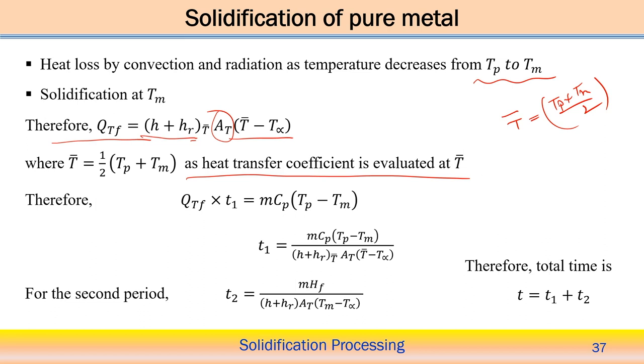So Q into t over the time t1, for example, is the total heat transported over the time t1 to reach from peak temperature to the melting point temperature. The total heat release is m Cp (Tp minus Tm), the specific heat without phase change. So t1 can be m Cp (Tp minus Tm) divided by Q, which equals (h plus hr) defined at the average temperature of peak and melting point temperature, times the cross section area and the temperature difference, the average temperature minus T infinity. This is the time required to reach from Tp to Tm.